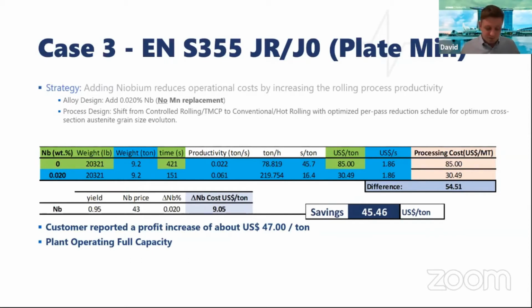This is a very interesting case because this company used to operate full capacity and they're not allowed to roll the whole year long. So they have a limited amount of months of the year that they can produce. So everything they produce more or every productivity improvement is just margin in their pocket. And in another thing specific about this mill is that they have a high production of lower than 30 millimeters thick plates, which is very important for this concept, because the lower is the thickness, the more amount of passes you have to do, the more the Nb can improve your productivity.